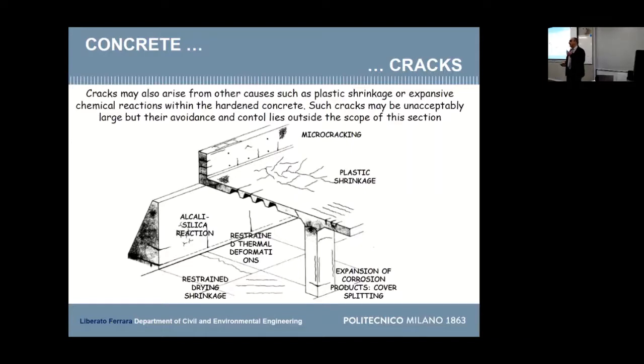So this is what we generally do for cracks which are caused by mechanical actions, which can be forces, or restrained deformations that induce stress. But there are a number of phenomena that can cause concrete to crack that we do not know how to handle, how to calculate the width of crack due to this. And most of these phenomena really occur at very early ages of concrete. For example, plastic shrinkage is due to differential evaporation. You have a gradient of water.